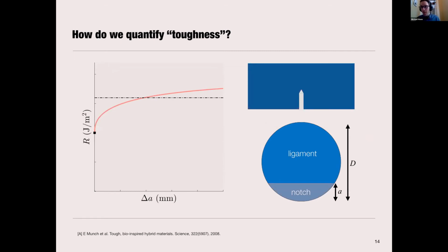So from this, how are we going to quantify toughness? How do we measure toughness? I really looked at this from the perspective of a crack growth resistance curve. A representative crack growth resistance curve with a rising R response is shown here in pink. That shows that as the increment of crack length, delta a, increases, the crack growth resistance also increases due to a number of factors.